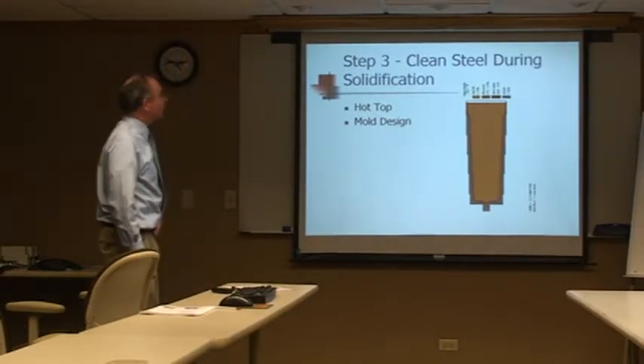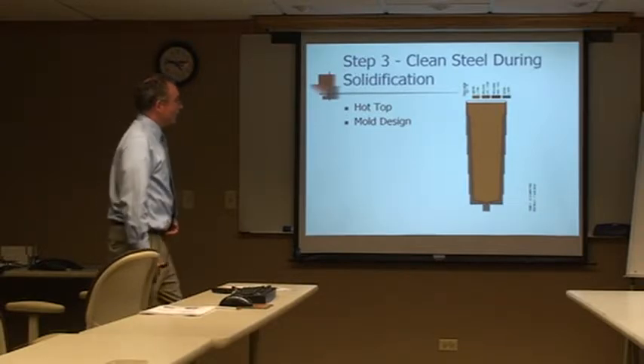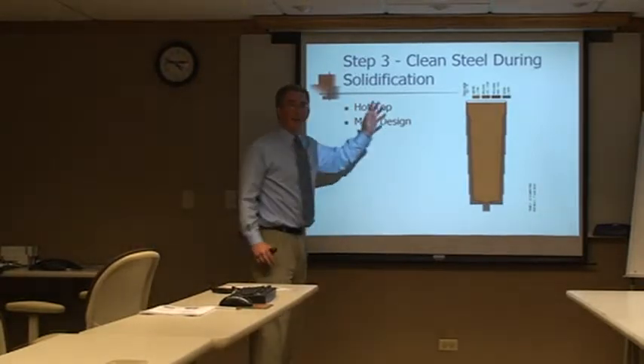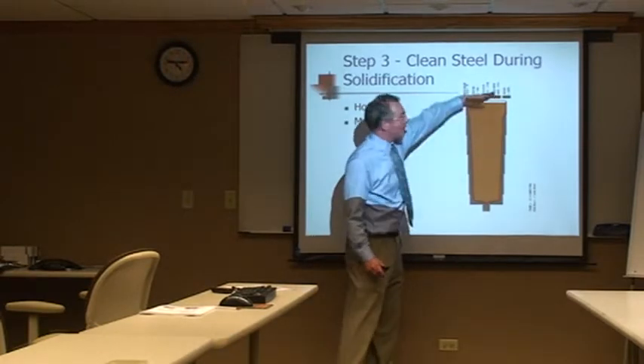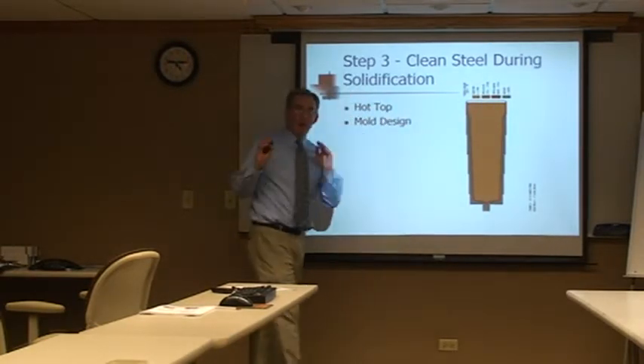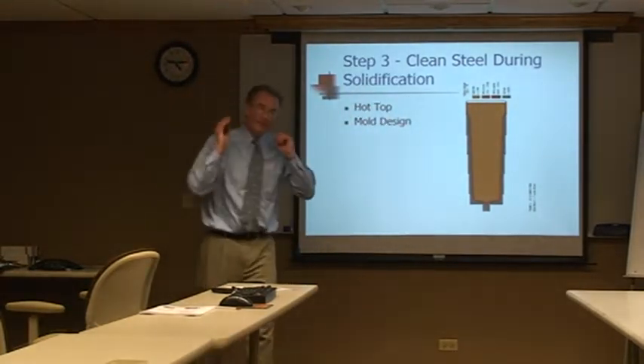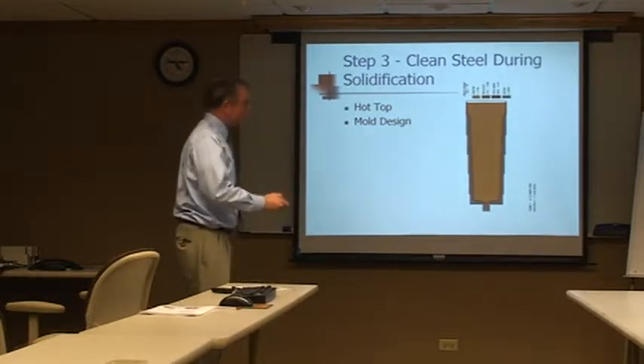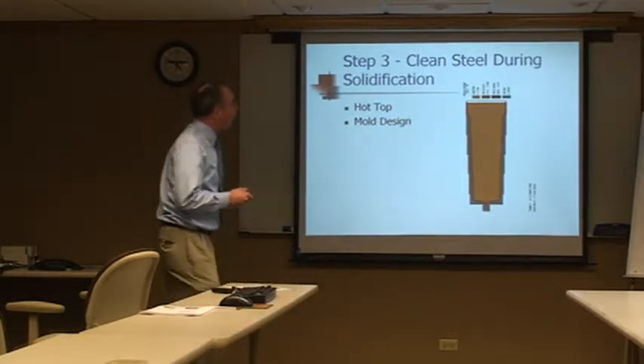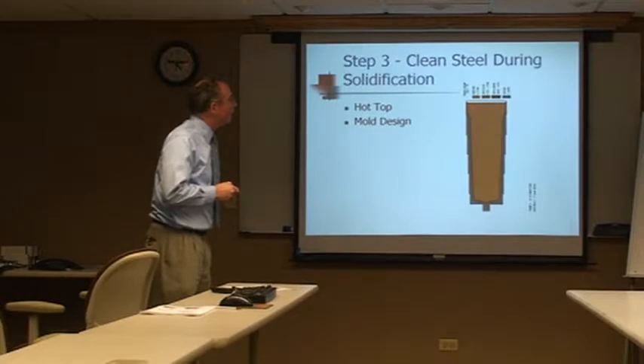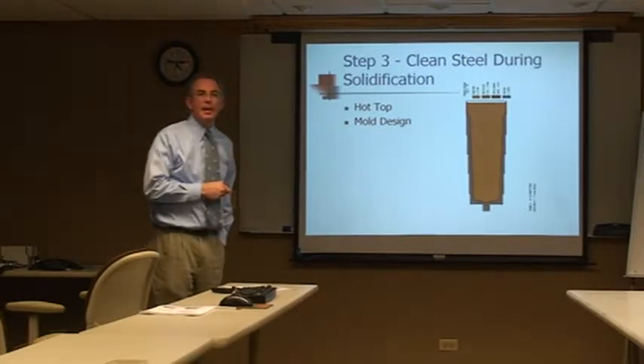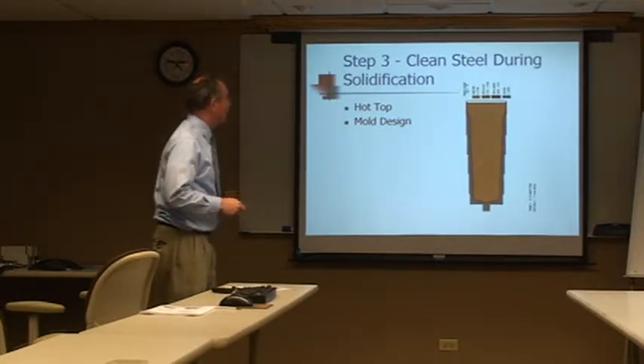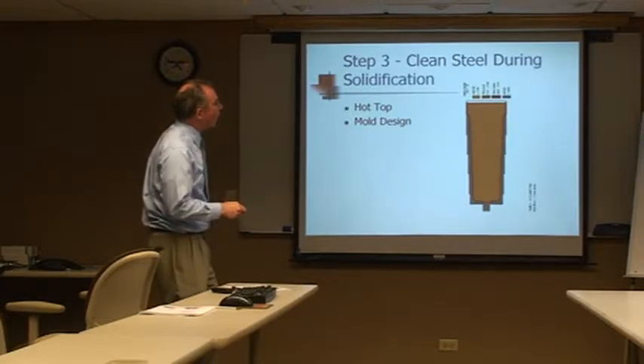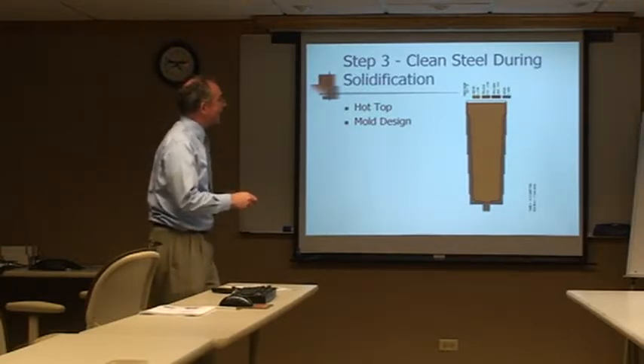Okay, clean steel during solidification. So now we've deoxidized the steel. We've successfully poured this ingot at a controlled rate of rise. We have not entrapped any teaming flux, which is good. What we have here is a finite model of an ESR ingot, a 49-inch diameter ingot. This is 15 minutes after pouring. We're going to watch this solidify.